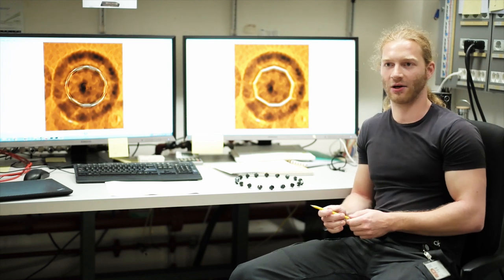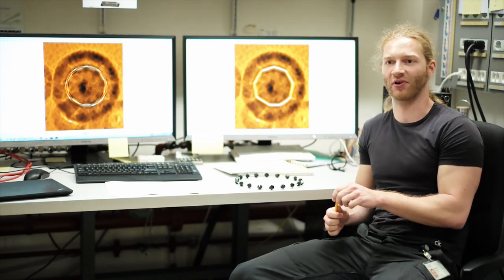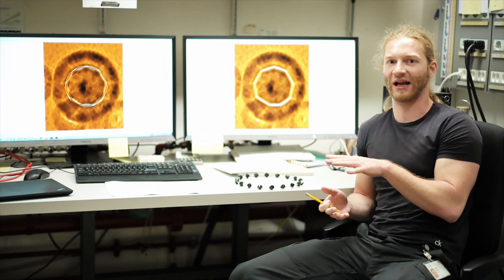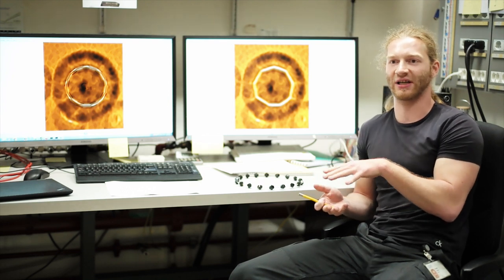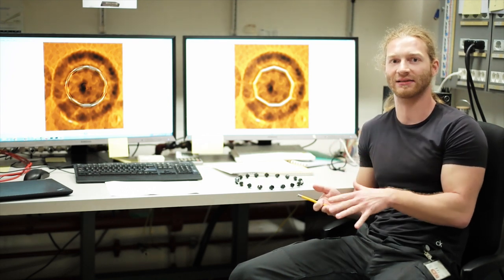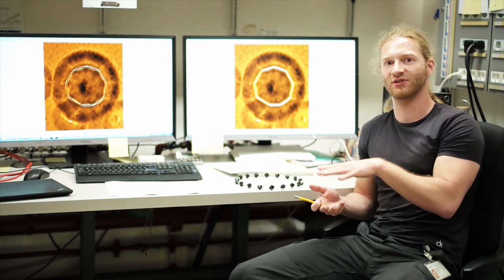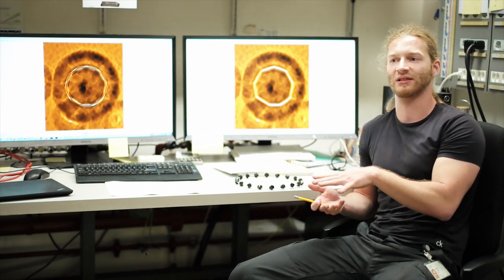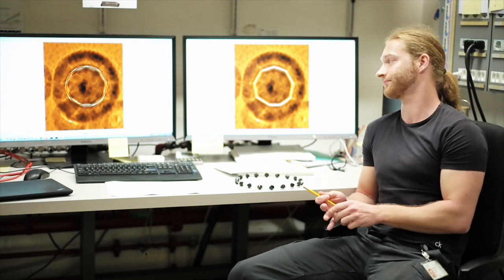Now, in order to find this out, what we can do is simulate atomic force microscopy images. So we first calculate the theoretical structure of cyclocarbon using quantum mechanics, and then we can use another code to simulate atomic force microscopy images, how they would look for different structures.